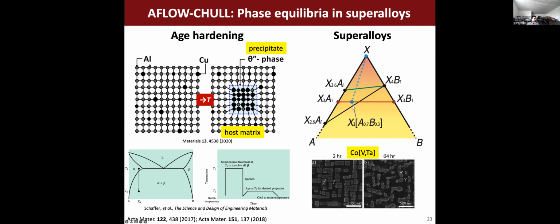Okay, so we look at a system here, an aluminum copper system. The host matrix there's really a lot of aluminum and there's a bit of copper in the system, and we can perform a particular heat treatment. We increase the temperature very rapidly, decrease the temperature rapidly. This is called quenching, and then we do an annealing at a lower temperature. This is going to result in the formation of precipitates. In the middle here, you can think of them as like nuts in your brownie, right? Where inside of the greater host matrix, which has the composition of this aluminum copper system, we get another phase, which in this case looks like it's more copper than aluminum, this precipitate.